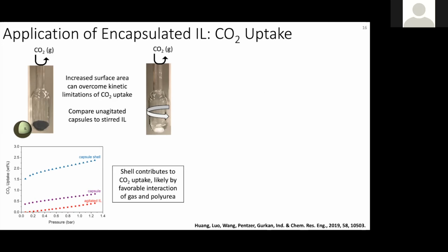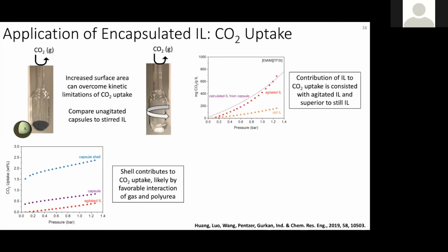So again, there's opportunities to play with the chemistry. But if we subtract out the contribution of the capsule shell, we see that the ionic liquid uptakes the same amount of CO2, whether it is encapsulated and unagitated or bulk and agitated and stirred. And then the yellow data here shows that if we have the ionic liquid unagitated, we actually never reach equilibrium.